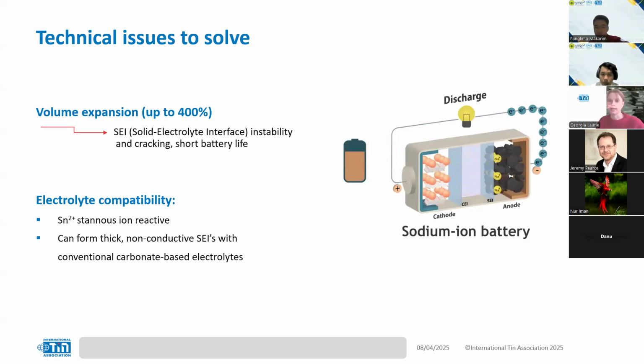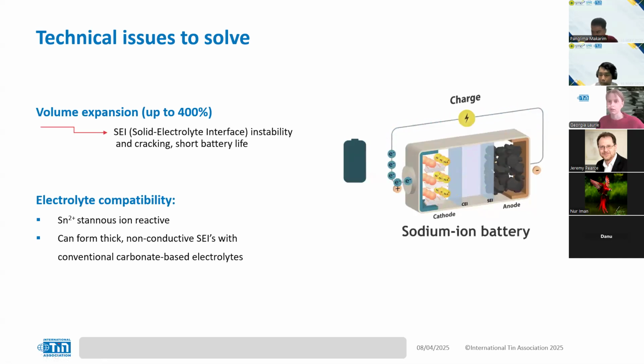Another challenge with using tin is electrolyte compatibility, which you can see in the middle here between the CEI and SEI. This is the electrolyte material where the ions flow through to insert and leave each electrode material. Tin ions, specifically the Sn2+ stannous ion, are incredibly reactive and can form thick, non-conductive SEIs when using conventional carbonate-based electrolytes. These SEIs can therefore reduce the overall performance of the battery and again lead to short cycle life. What I mean by SEI is the solid electrolyte interface, which is a layer formed between the electrolyte and the anode material. You can see it here. This is actually essential for stopping direct contact between the electrolyte and the anode material, which, if broken, short circuits the battery.